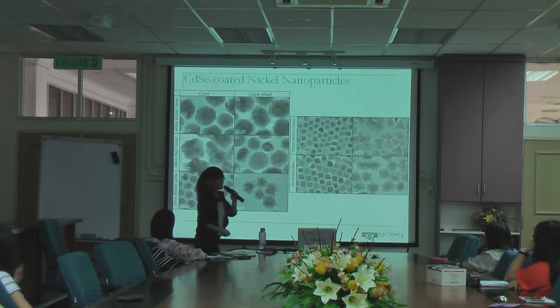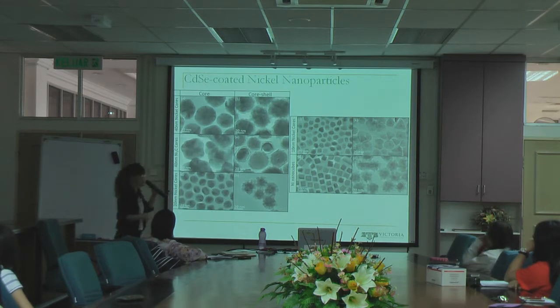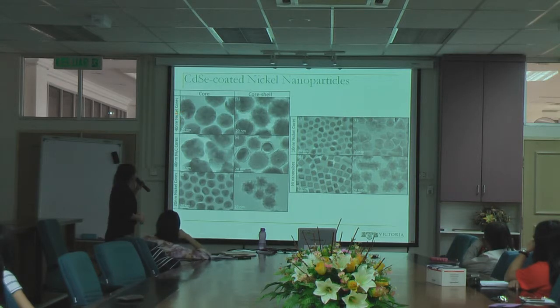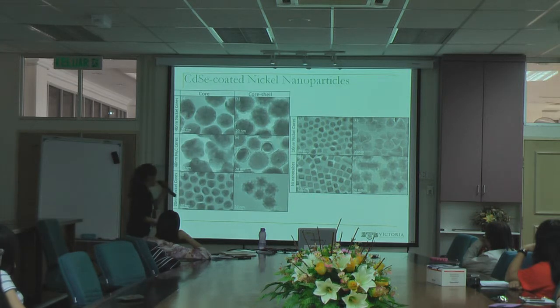So let's take a closer look at the morphology of the cadmium selenide shell. We can see that in some cases there are some similarities, and in some cases the morphology of the cadmium selenide shell is quite different. So for example, 40 nanometer nickel, 20 nanometer nickel, and nickel nanocubes, they have very similar morphology of the cadmium selenide shell. Essentially, the nickel particles are covered with small particles of cadmium selenide, which are about 5 nanometer in size. What about the other cases?